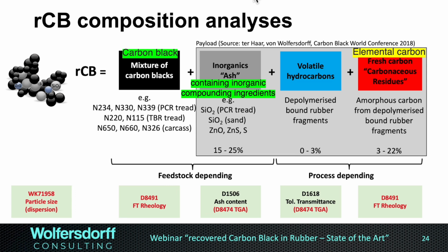And the tests really, now we can look at material by material. How do we test the fresh carbon, the carbonaceous residues, really by the rubber performance? And here we have a fantastic test developed by Continental Tire, by Jorge Pineda. This is the Fourier transformation rheology. It is accepted by ASTM. It is D8491. What do we do here?